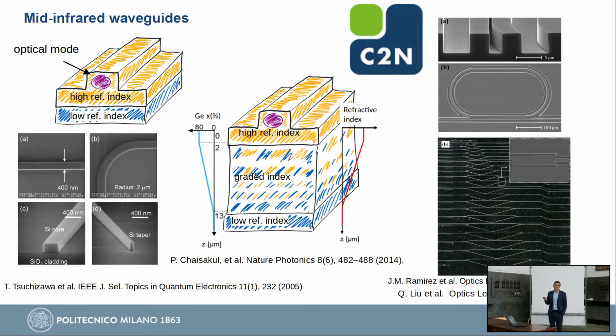But we are interested in sensing, so we want to move to wavelengths which are not 1300 nanometers, but actually microns. And to do this, we exploited a different approach, and the two materials are now silicon and germanium. I was telling you before that germanium has a higher refractive index than silicon. So if I make a structure like this, I start from silicon, I slowly increase germanium until I have a very high germanium content here. My optical mode will try to be confined in the upper part, okay? And so here you see the grading in the composition will correspond to a grading in the refractive index.